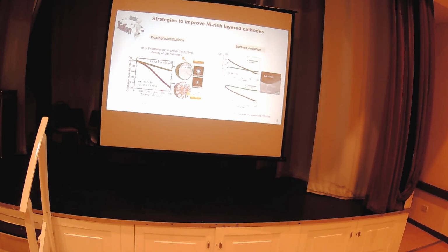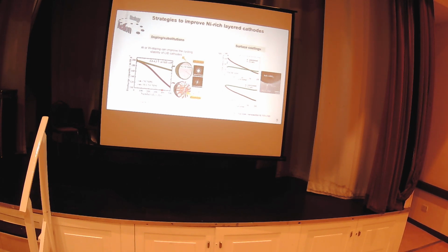And the second is coating. We can also coat with different materials. The first example is alumina, Al2O3, which again stabilizes the surface. That means we don't have oxygen or gas release in the battery. It not only improves the cycle stability but also improves gas evolution in the cell, which means we can make it safer and keep high energy. This is a very thin film at the surface, about 10 nanometers, which we can't see even with our eyes. This is done by different coating techniques. So these two strategies can be utilized to improve the cycling and of course the safety.